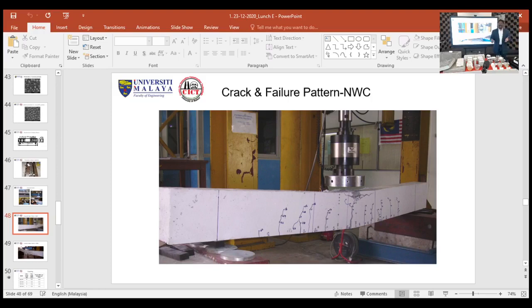And after the flexural performance test, we found out this is a conventional concrete, normal weight concrete, does not have multiple cracks compared to the oil palm shell concrete. We can see the cracks here, limited numbers. So what happens is because of the limited number of cracks, the cracks widen up, and there is a possibility of brittle failure. Whereas look at this similar beam, same size, same reinforcement ratio, but based on the oil palm shell lightweight concrete. So we can see numerous cracks on the surface compared to the conventional normal weight concrete.